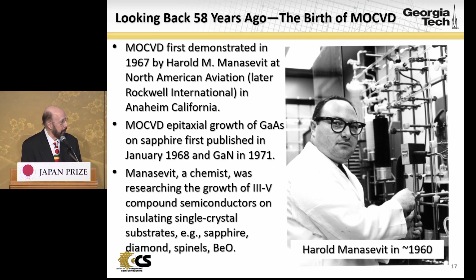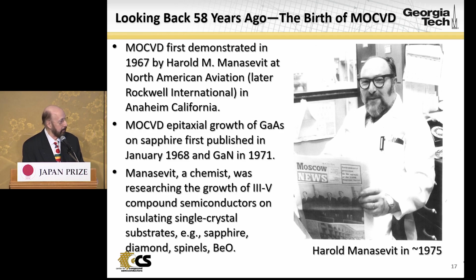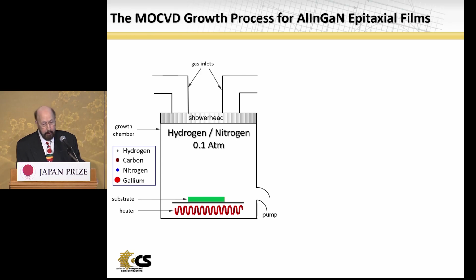This photograph is of Hal in around 1960 when he began his work, and this is a picture of Hal about 1975 when I first got to know him. MOCVD is a relatively simple process from the chemistry point of view, but in a practical sense is quite complex to control. So we typically use stainless steel growth chambers that are operating at low pressure, typically 1/10 of an atmosphere in a hydrogen-nitrogen atmosphere.